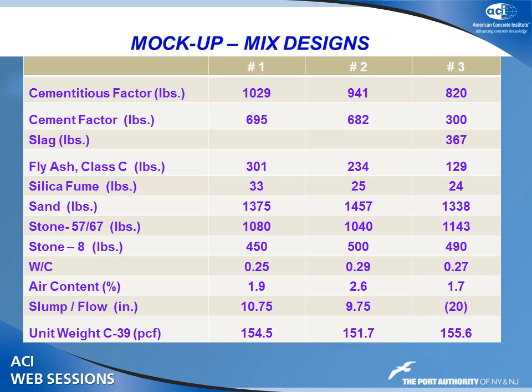Okay, when we got involved with this Freedom Tower, we knew that in New York City, we love to use a lot of cement and cementitious material in our concrete mixes, so we put in a specification that in-place temperature cannot exceed 160 degrees, delta T 35. So, why did we do that? Because we did not want 1,300 pounds of cementitious material, and no one would accept that.